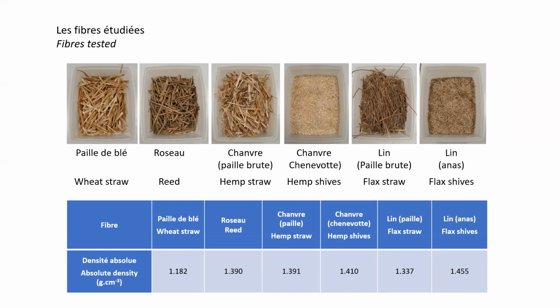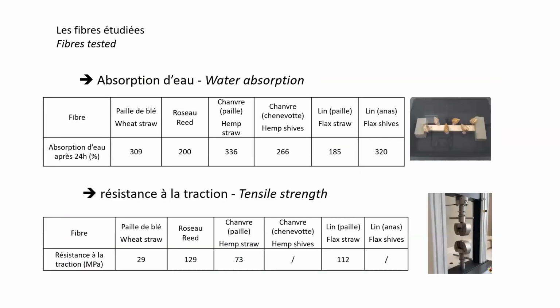So we studied these different fibers in the labs, first of all, on their absolute density, and this could give us some clues and information as to their capacity and their mechanical strength, compressive strength. So we saw here that wheat straw gave us fairly weak results compared to the other fibers we studied. We also tested these fibers in two other aspects that we thought would be quite interesting.